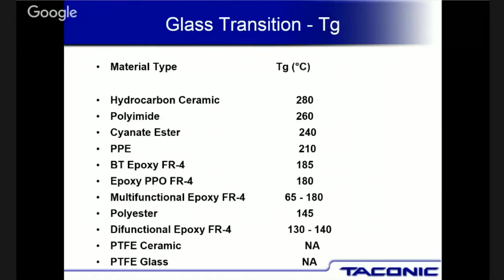It used to be you could take that board and put the components on it, run it through an IR reflow, and the board would come out the other end with all the components soldered in place, because you're exposing it to 210 degrees for a number of seconds over the IR reflow. With RoHS and lead-free solders, now we're looking at 280 degrees. And if you take a material that's made out of a difunctional epoxy with a T sub G of 130, and you run it at 280 or 290 degrees centigrade, that material is going to bow, twist, and warp, and could virtually fall apart.